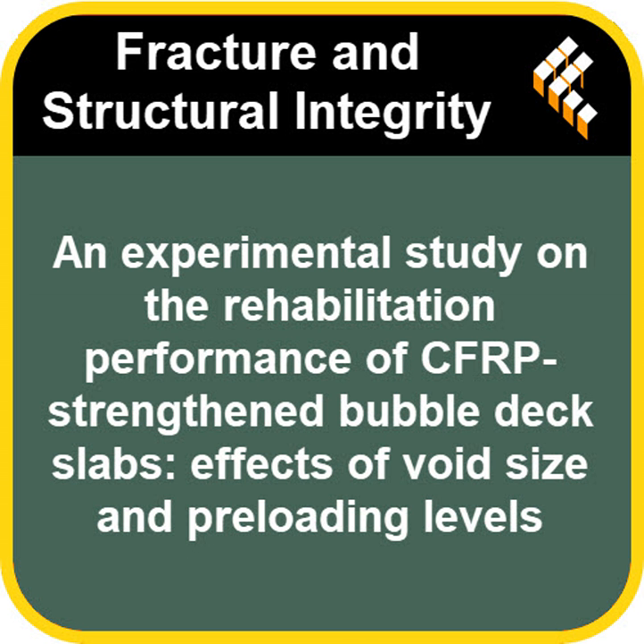So they didn't just test pristine slabs. You mentioned simulating real-world wear and tear. They actually damaged the slabs before applying the CFRP. How did they do that? Precisely. This is key. To simulate realistic scenarios, the slabs were preloaded. They applied load up to specific percentages of their ultimate capacity. That's the maximum load they could theoretically take before failure, before any CFRP was applied. Okay, what sort of percentages are we talking about? They chose levels of 50%, 60%, and even 75% of that ultimate load.